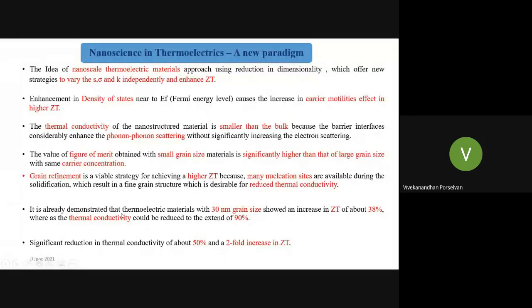So it is already demonstrated that a thermoelectric material with 30 nanometer grain size shows an increase in ZT of about 38%, whereas the thermal conductivity could be reduced to the extent of 90%. See, this is a great phenomenal effect only because of the grain size reduction towards nano. A significant reduction in the thermal conductivity of 50% will help us to get a twofold increase in the ZT, right? So if you can reduce the thermal conductivity by 50%, you can increase the ZT twofold. That is a ZT of 1 to 2. That much effect we can make.